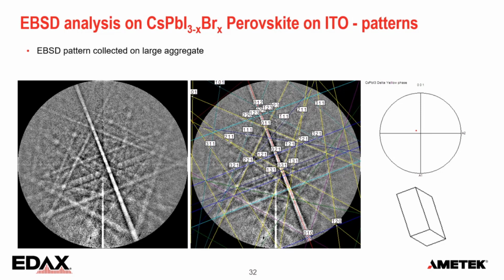But where do you get that? We can simulate it, we can calculate it, but the models are not perfect. Or we can get it, for example, from X-ray data, and all the large crystallographic structure databases, like the powder diffraction file from ICDD or the ICSD database, they're all based on X-ray diffraction. And X-ray diffraction and electron diffraction may give totally different intensities for specific lattice planes.